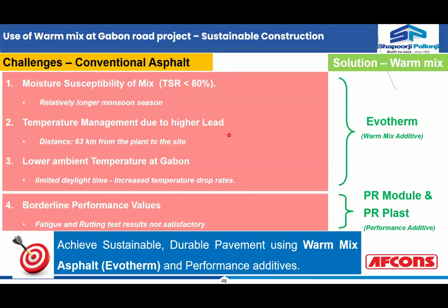So when you talk of warm mix, we have used a material called Evotherm, which is an additive used to control the moisture susceptibility of the mix. Moisture susceptibility is a test which is based on the type of the aggregate. If your aggregate is moisture susceptible and you don't have any other option but to lay it, it's always good to use Evotherm as an additive in the asphalt, which will coat your aggregate in such a way that this particular test will never fail.